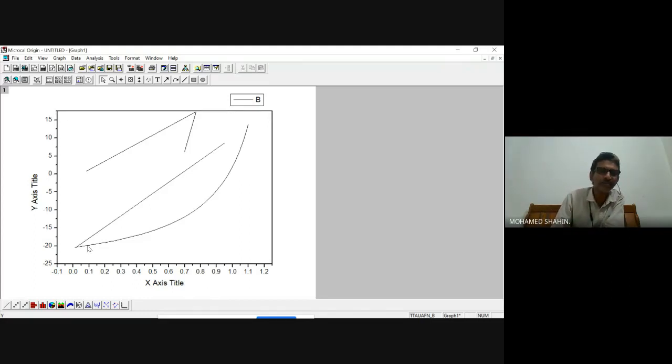Our strong systems would be having almost straight line behavior. But a fragile system is not like that. It will initially be going approximately parallel to the x-axis, or the slope would be lesser. Then all of a sudden, around the glass transition temperature, the slope increases, and that is the fragility. And fragility can vary between 25 to 200.